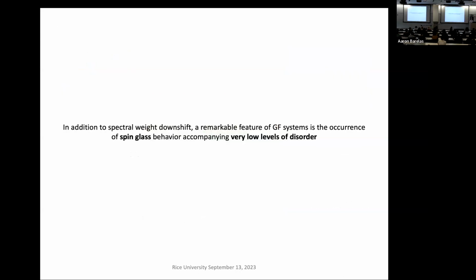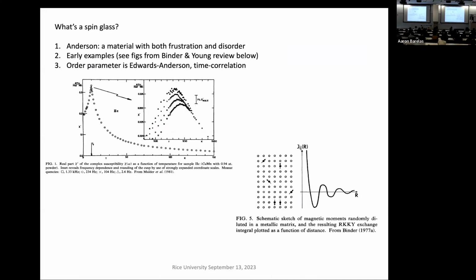Okay, so in addition to spectral weight downshift, a remarkable feature of geometrically frustrated systems is the occurrence of spin glass behavior accompanying very low levels of disorder. And this was a big surprise. So just let me explain what spin glass is. From an experimental point of view, a spin glass is a material that has a cusp that's frequency dependent. These are taken at different frequencies.